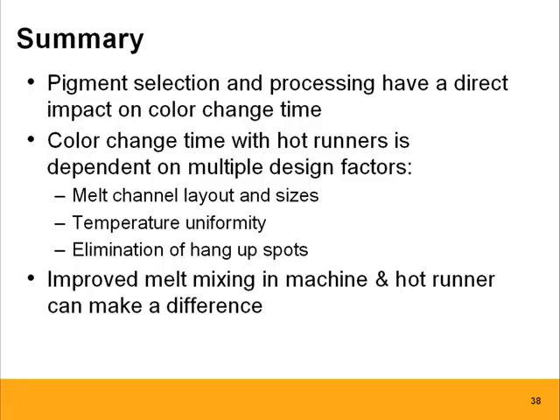Color change time with hot runner is really dependent on three factors. The melt channel layout and sizes should be optimized for color change. Temperature uniformity, as I pointed out, has an effect on how much boundary layer we create within the melt channels. What we especially have to look out for from a color change point of view is cold spots in the hot runner system. And then, of course, we want to eliminate any kind of hang-up spots within the system.